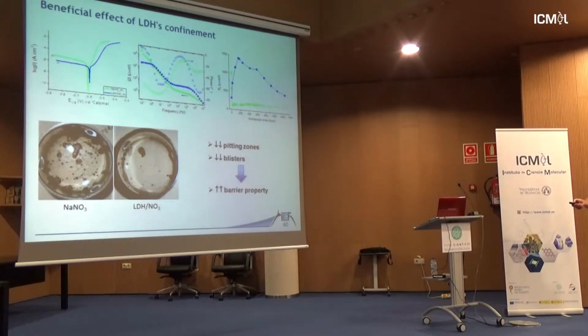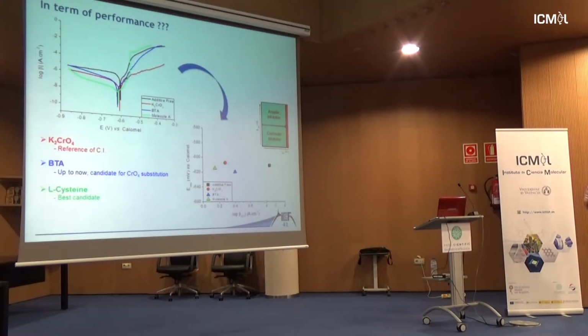So that's intensity versus potential, and that's the impedance, total impedance as a function of the frequency. And we get quite a nice result, because if you compare, chromate here in red is quite a nice corrosion inhibitor. But if you look at BTA, or benzotriazole, that has been identified in the literature as the most appealing or compelling additive to replace chromate. In fact, we have an even better solution using L-cysteine. It's an amino acid with a thiol group and an amino group, interleaved into LDH, and it is acting as a very good inhibitor.